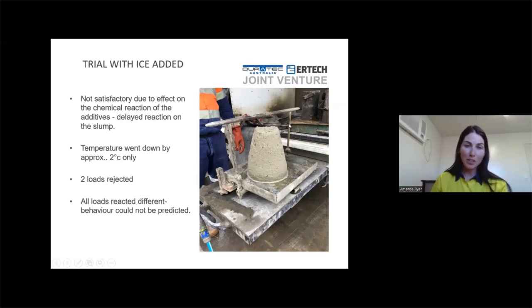As you can see here, it's a pretty low slump, as our slump specification was 160 plus or minus 40. This slump, I think I remember, is 80 mil, which is way out of spec.